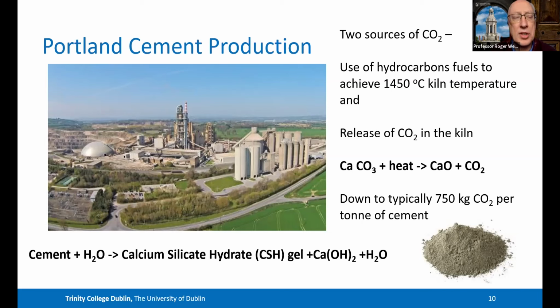And that's important because if you're using less cement, you're going to have less calcium hydroxide. And calcium hydroxide is important for giving concrete one of its properties, which is that it's an alkaline material. And because it's an alkaline material, it helps to protect steel reinforcing bars, and indeed pre-stressing tendons in concrete. So if you reduce the cement content, there's a risk that you might reduce the protection of the steel and create a durability issue. So one of the limiting criteria we have is to use a minimum amount of cement.